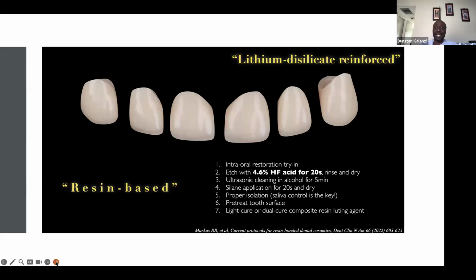But if you have a milling machine in your practice and you have an oven, so you're sintering and everything, you need to do this processing yourself. After you have sintered, you need to treat the surface before cementation. So that's where this comes in. Because a lot of this is not being done by the lab, but in the office, you need to know how to treat the surface before you cement the restorations.